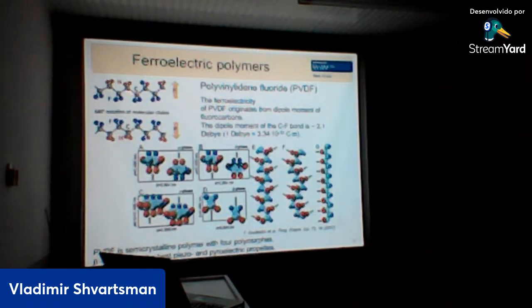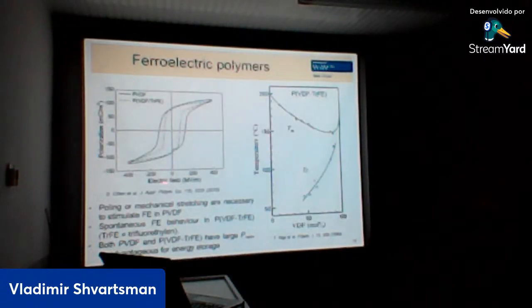So in these materials, we have such chains, and we have fluorocarbon and fluorohydrogen bonds, and this fluorocarbon bond is strongly polar and has its own dipole moment. And when we have a specific conformation of this polymer, the so-called beta phase, then the dipole moments of the individual bonds are ordered. So we have long range order, we have ferroelectric state. So again, we have ferroelectric polymer, and even better when we add trifluoroethylene as a copolymer, but this is ferroelectric material. And we say that ferroelectrics are not good for electrical energy storage.